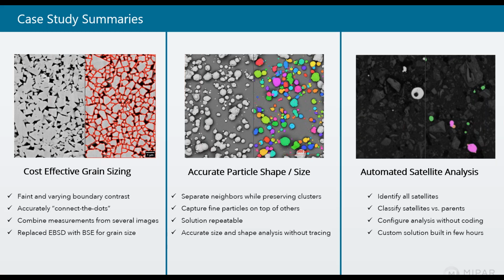In the second case, the user was stuck using inaccurate automation to produce inaccurate shape measurements because it's the best that they had. With a MIPAR recipe, they were able to reliably separate overlapping particles, even tiny ones that sit entirely on top of bigger ones, and they were able to preserve these more complex clusters and not over-separate them, because once they do, they really couldn't get an accurate shape measurement. And as an unexpected side benefit, the ability to accurately capture these small features that sit on top of others allowed them to switch to image analysis for their sizing and get a much more accurate size distribution than their laser approach allowed, since their laser approach grouped clusters like this into one feature and didn't count the size of the small ones.